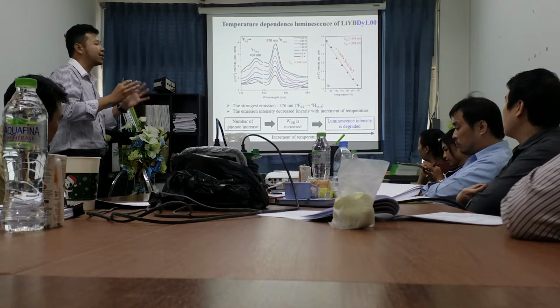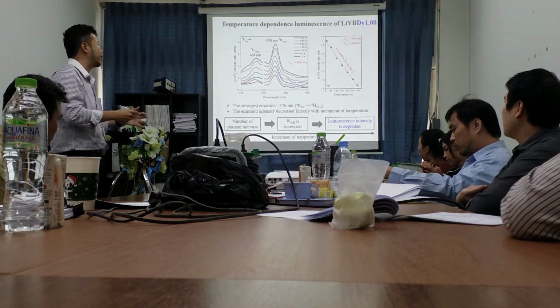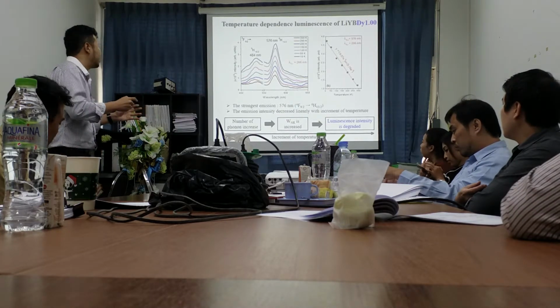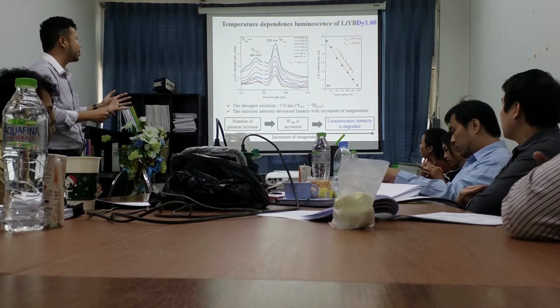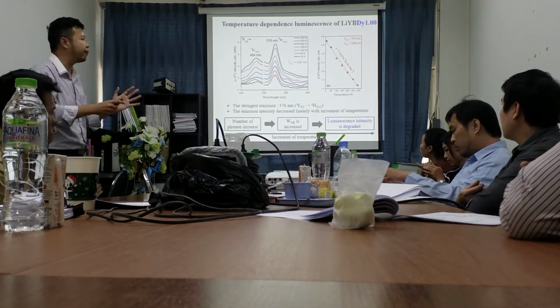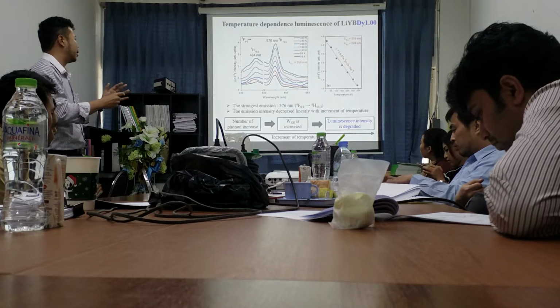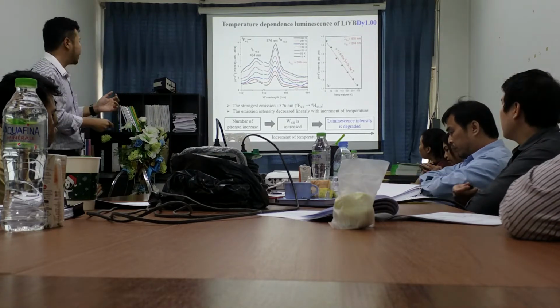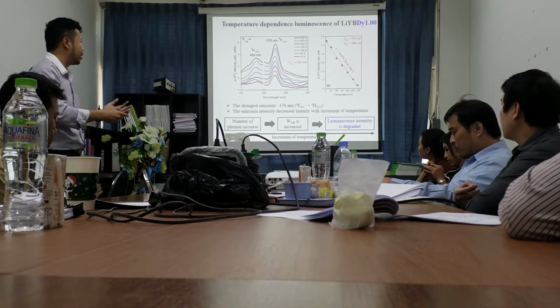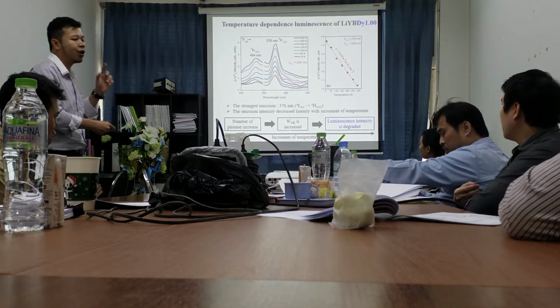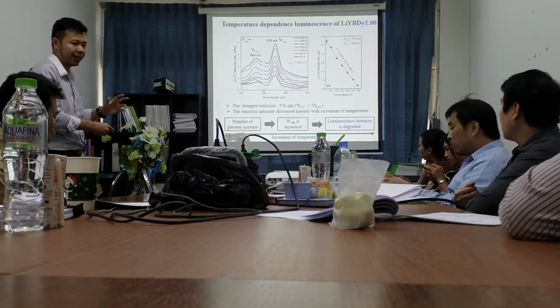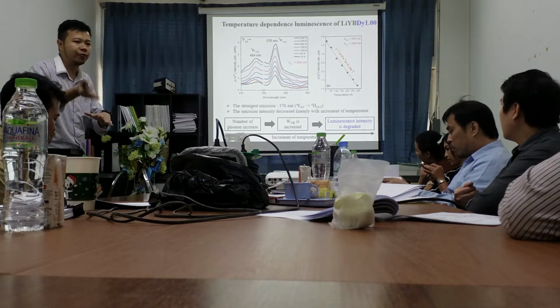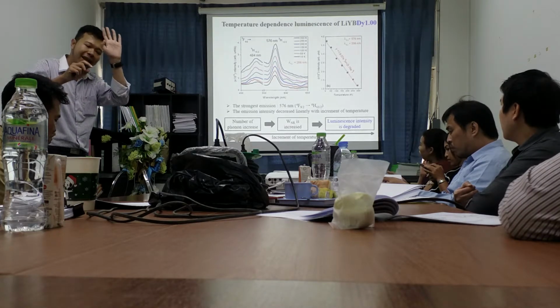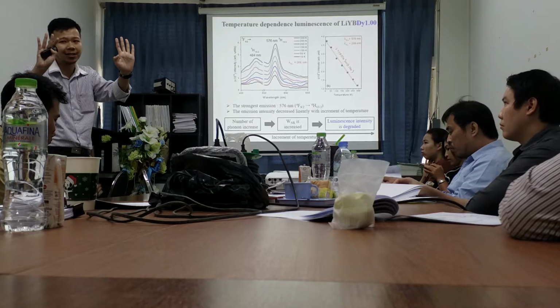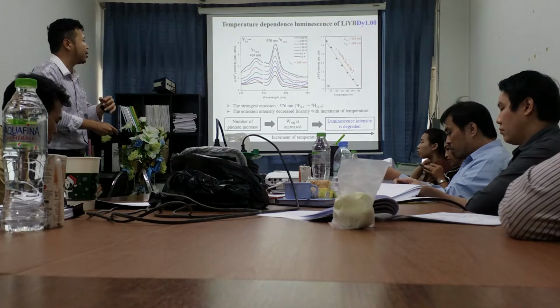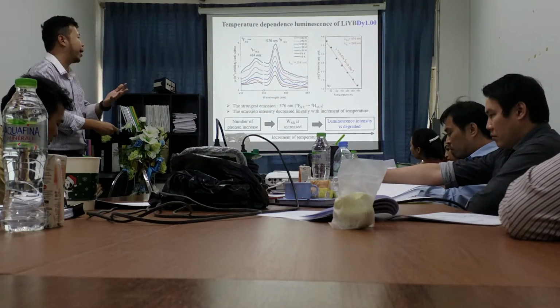We found just two peaks of the dysprosium ion because of the weak signal. And the intensity of the luminescence decreased with increasing temperature. Because when the temperature is higher, the number of phonons increases, and the non-radiative transition rate increases. And I told you before, it is a competition between radiative transition and non-radiative transition. If NR is high, luminescence is low.